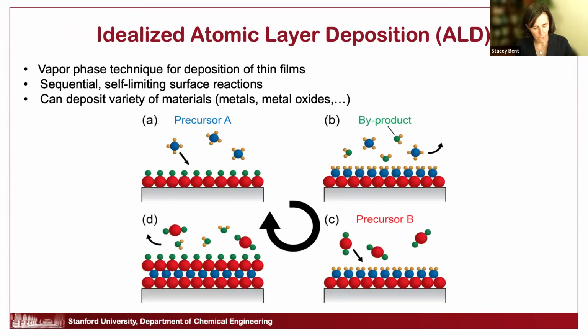This is a process that's been around for about 60 years, but has been becoming more and more important to microelectronics fabrication over the last decade or two. So it's a vapor phase technique for depositing thin films using these sequential self-limiting surface reactions. So typically two different precursors will be flowed in sequentially. Each one of those undergoes a self-limiting reaction so that one ALD cycle will deposit at most one atomic layer.